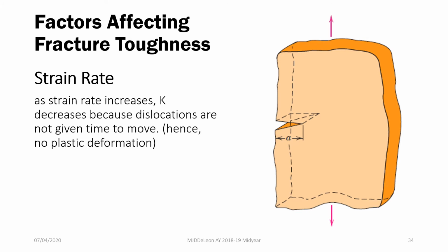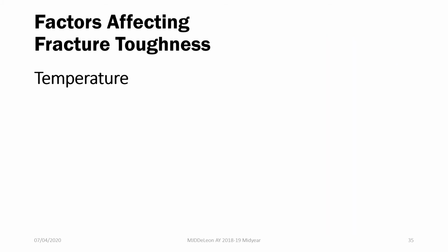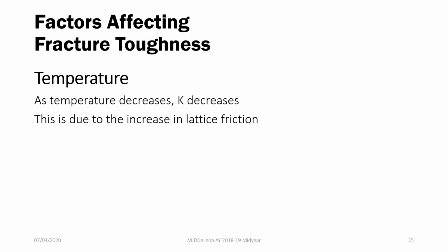If mas mabilis yung strain rate mo, the fracture toughness of your materials decreases or it is more susceptible to fracturing since we're not giving our dislocations enough time to move about. Hence, there's no plastic deformation, bringing us to fracture. So now for temperature, if we increase our temperature, we increase the fracture toughness. Consequently, if you decrease the temperature, you also decrease the fracture toughness of your material. This is due to the increase in the lattice friction of your material as the temperature decreases. Makes plastically deforming the material harder, making fracture easier.